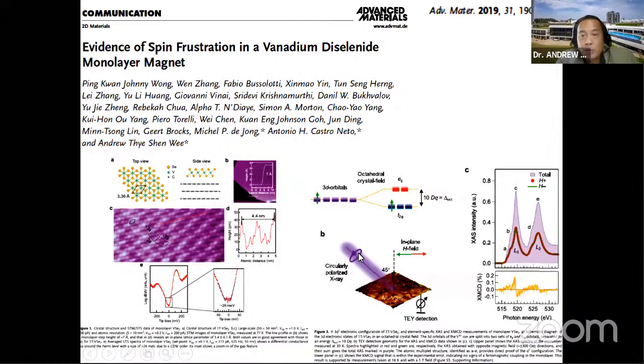And what is more important, when we use circularly polarized X-rays and take the difference between the left and right circularly polarized X-ray from the X-ray absorption edge of vanadium, we can get what is known as the circular dichroism magnetic signal from vanadium. You can see that taking the difference spectrum, the percent of signal is extremely small. It's 0.1 or so, which in effect is around the noise level. So we had a lot of difficulty measuring any magnetism in our MBE grown vanadium diselenide.